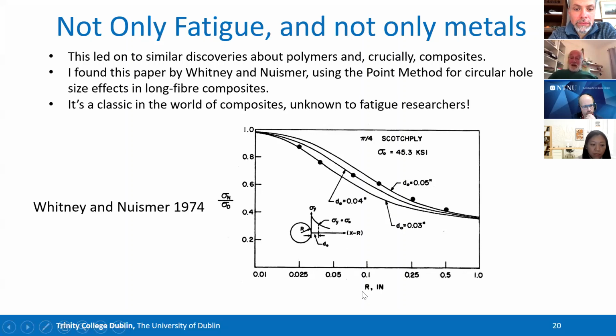You see what's happening when the radius of the hole is large enough, you're getting down to a point where you see the full stress concentration factor, the KT factor of 3, because it's coming down to 0.3 here. Whereas if you have a very small hole, then you've got no effect at all, and you come up to 1, and all these real holes are somewhere in between. But they're using exactly the same critical distance approach.